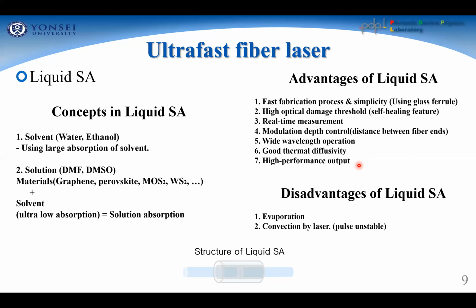By tuning the air gap, we can control the modulation depth, and it offers wide wavelength operation, good thermal diffusion and high performance output. But the disadvantage of the liquid saturable absorber is the evaporation and convection of the liquid, so we have to deal with it carefully.